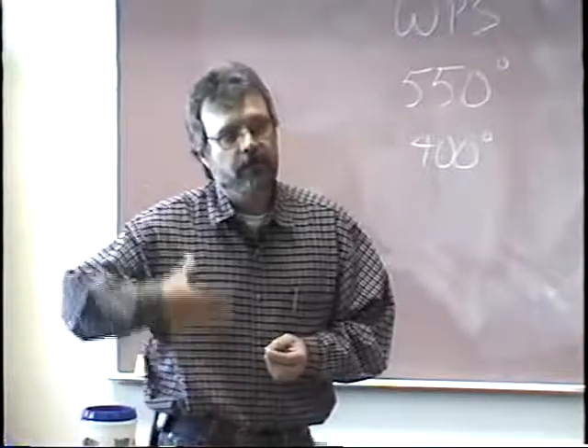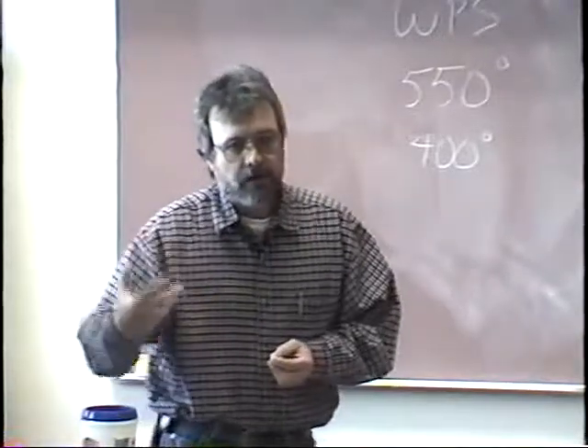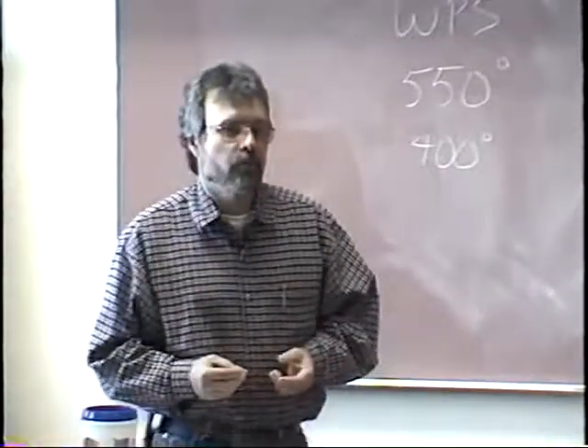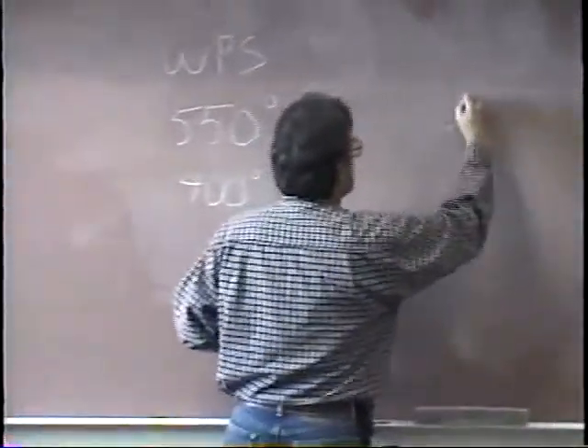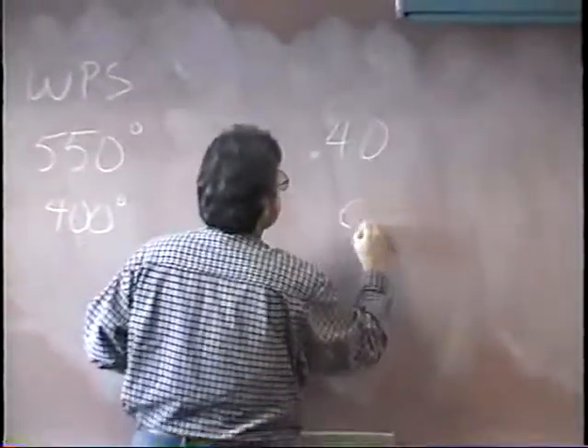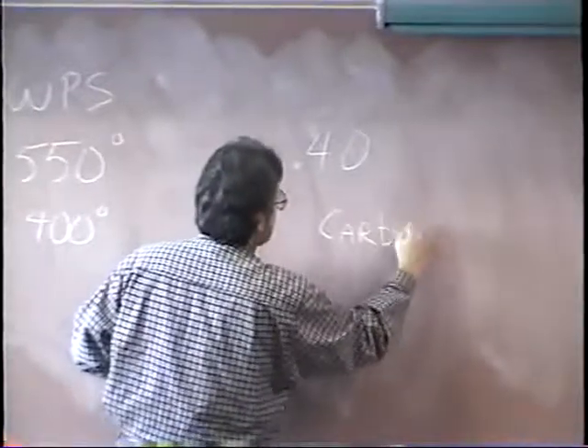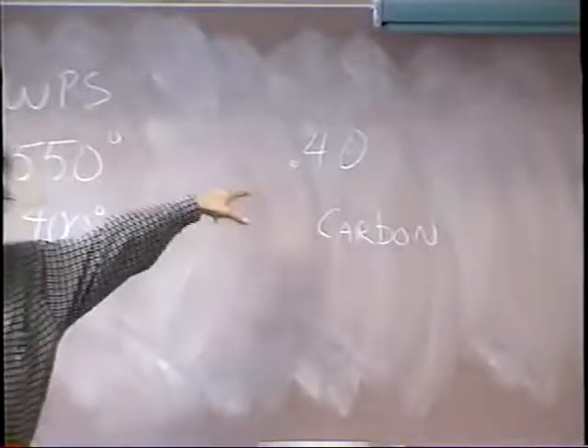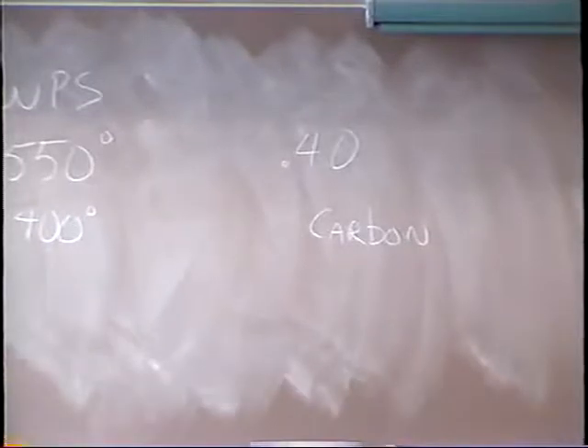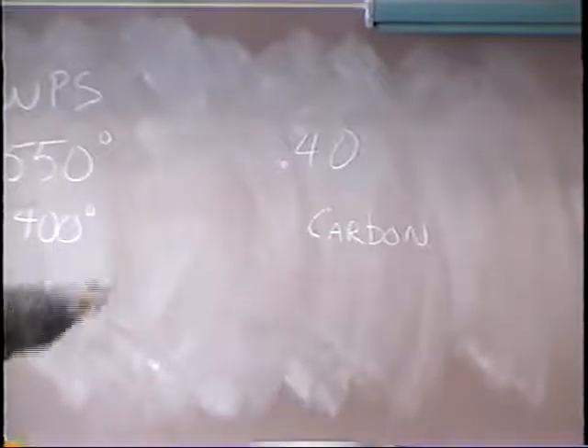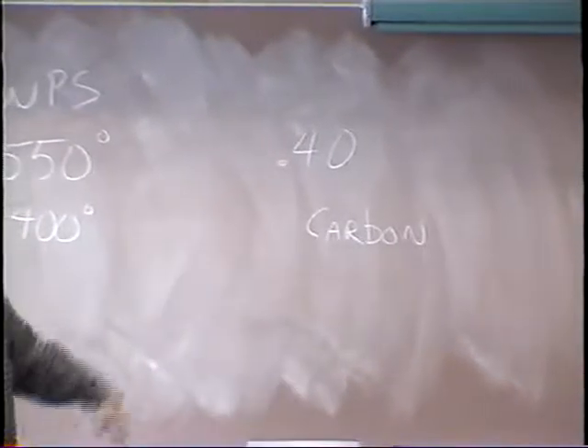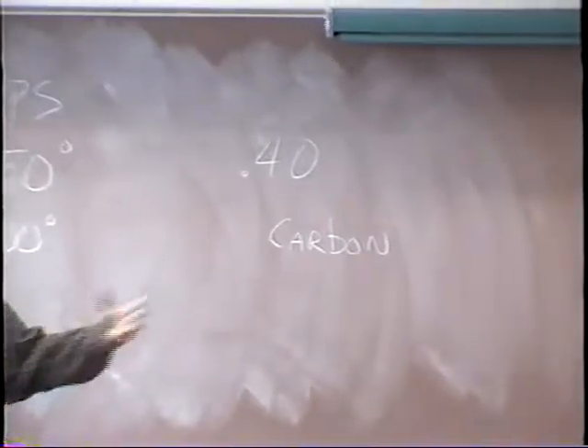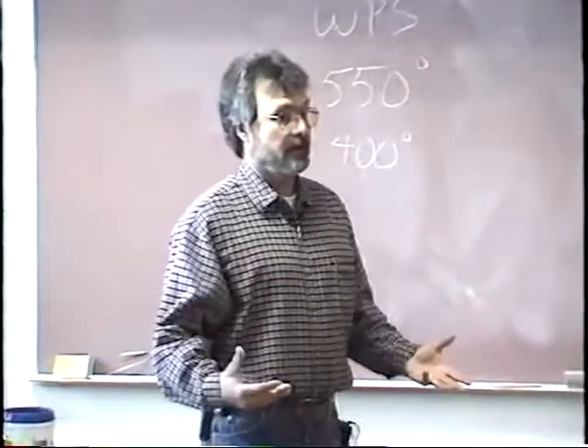brittleness, and hardening. If you get more than .25%, and actually most texts will tell you more than 0.4% carbon, that's considered a high carbon steel. Anything above, now think about that. If you had 100 pennies, if you had a piece of pipe and let 100 pennies represent that piece of pipe, that would be less than 1/2 of 1 penny amount of carbon mixed in that mixture. Well, that's not very much, but that's enough to give it such strength that it's susceptible to cracking.